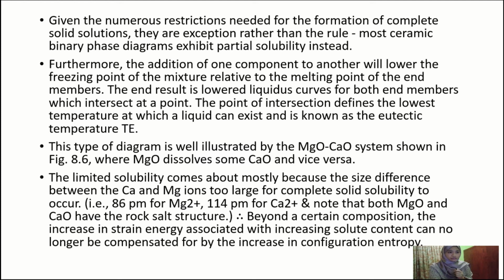This type of diagram is well illustrated by the magnesium oxide-calcium oxide system shown in Figure 8.6, where magnesium oxide dissolves some calcium oxide and vice versa. The limited solubility comes about mostly because the size difference between the calcium and magnesium ions is too large for complete solid solubility to occur. Beyond a certain composition, the increase in strain energy associated with increasing solute content can no longer be compensated for by the increase in configurational entropy.